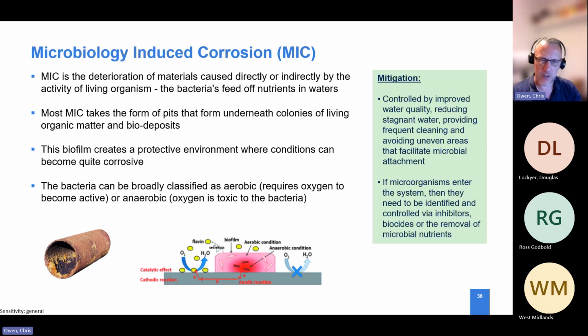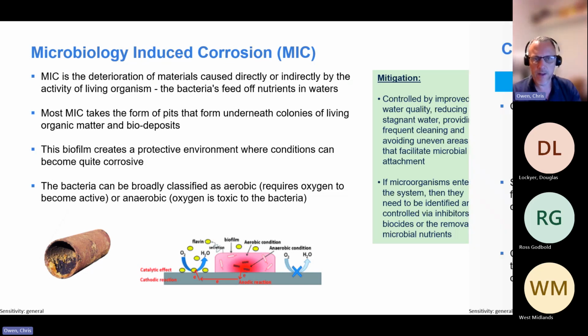Pipework was being commissioned, it was basically being water tested, and then drained down. It was leaving water behind, which was then breaking down to produce these biofilms. Those biofilms were not becoming stable. They were basically active, and because of the thin wall, they were resulting in very localized pinhole corrosion. So again, understanding what's in your system, and understanding that if you are doing flushing, there are certain things which can be added to try and reduce the risk of biofilms taking place.